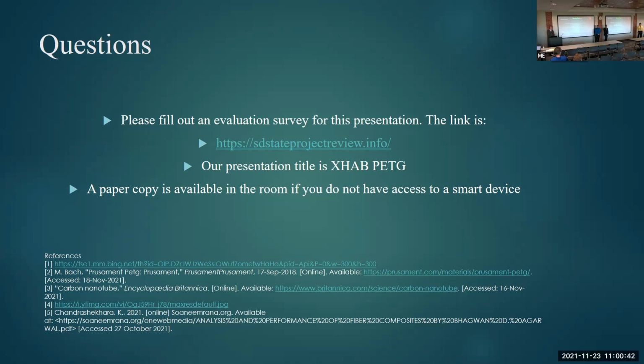Why did you stop at 2% mix? We went all the way to 10. I only showed 2% because previous studies that we found show that those equations start to become inaccurate around 5% for sure. So I wanted to be conservative in my guesses, so we only showed up to 2%. Also, the cost of the carbon nanotubes is a big concern there as well, if you get up to 10% versus the printed material.